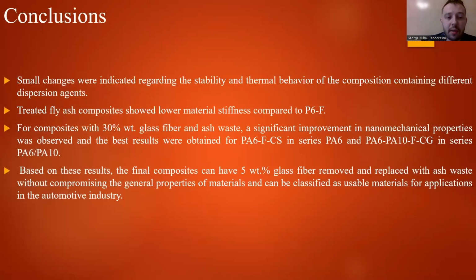So in conclusion, by introducing 5% treated ash in glass fiber reinforced composites based on polyamide 6 or PA6-PA10 mixture, composites were obtained with similar thermal stability to PA6 with 30% glass fiber at the processing temperature. They have improved flexibility due to the plasticizing effect of the surface treatment agents, and improved surface properties based on rigidity and hardness values, especially when using the silane coupling agent.